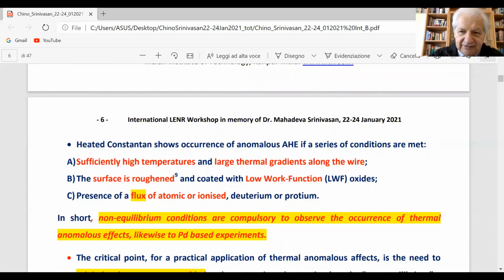The Constantan gives [the effect] when there are some specific conditions. High temperatures, meaning larger than 600 degrees more or less. Large thermal gradients along the wire, so it means non-equilibrium. The surface is roughened, like a sponge, that is coated with low work function materials. This is a key aspect of our procedure.